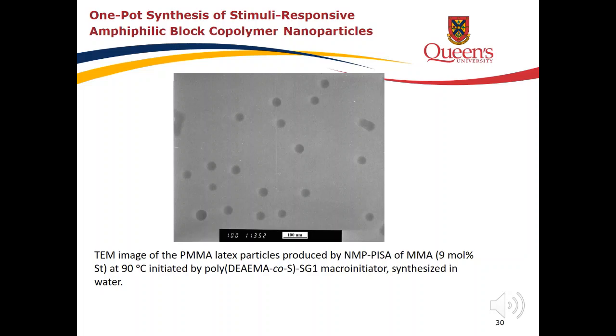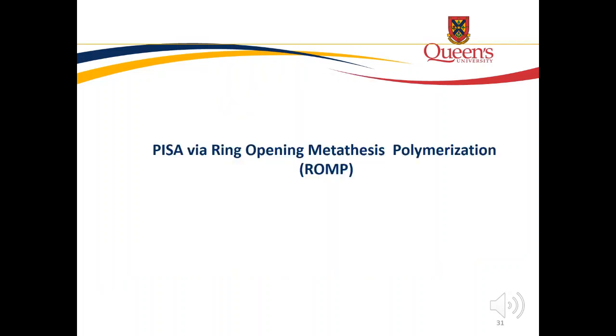Any of the conventional light or particle measuring techniques, for example, dynamic light scattering, will not tell you anything about shape. So TEM, SEM, and AFM are the preferred characterization techniques for getting a sense of what shapes you have, or what combinations or range of nano objects you're making in your PISA process.